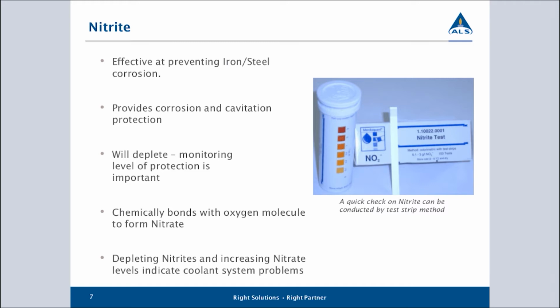On screen, we've got a little dip strip type methodology that can be used. This is very useful for a workshop or field environment for checking the coolant state. In the lab, we will use redox reactions or other methodologies for measuring exactly how much nitrite is still there and how much has been converted to nitrate. Essentially, for people unfamiliar with this, you will dose the coolant with sodium nitrite. When nitrite reacts with oxygen and becomes nitrate, it basically just means it's got an extra oxygen added to the molecule. Once it becomes nitrate, it's no longer effective in the system. So by monitoring both compounds, we can see the conversion rate from one to the other.